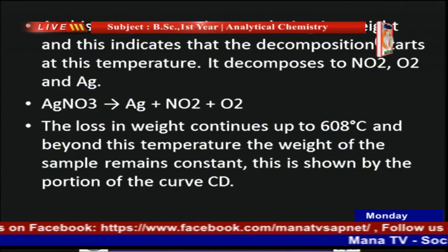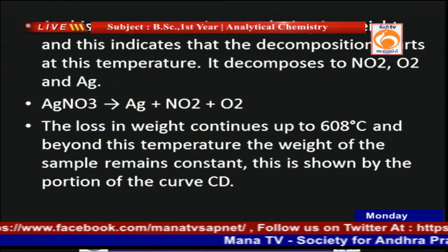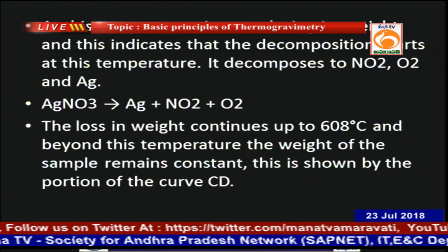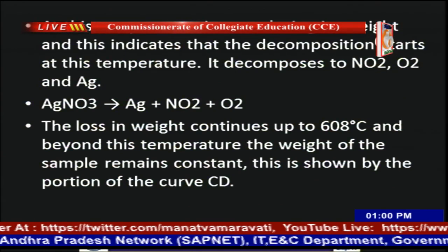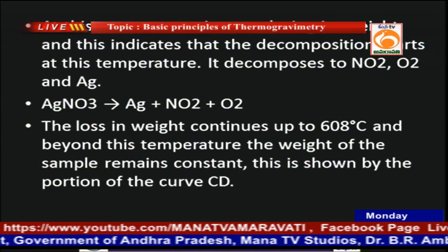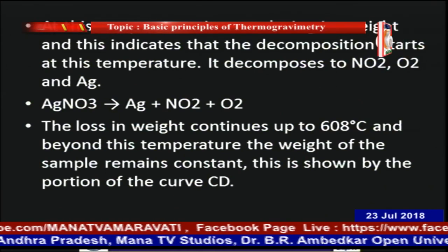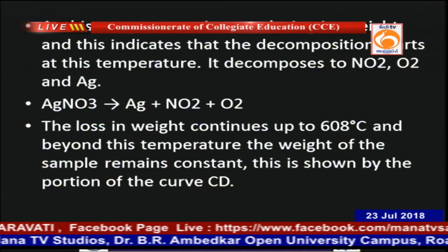So, what will happen when silver nitrate is heated to elevated temperature? It gets dissociated into silver, oxides of nitrogen and oxygen. So, this is the observation. We start seeing this after 473 degrees, and we will start measuring the loss in weight, which continues up to 608 degrees. So, from 473 degrees to 608 degrees, the changes are happening in such a way that by the time it finally comes to 608,